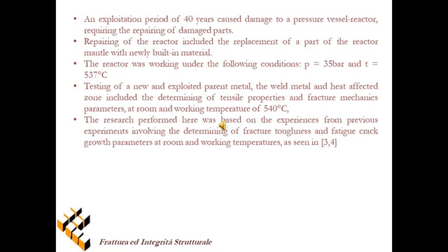resulted in the need to repair the reactor by replacing a part of its mantle with newly built-in material. The reactor was designed to work at a temperature of 537 degrees, and for that reason tests were performed on both new and exploited parent metal, weld metal, and heat-affected zone at both room temperature and a working temperature of